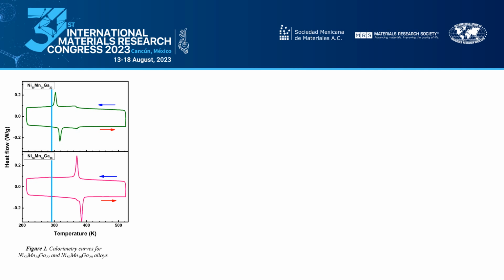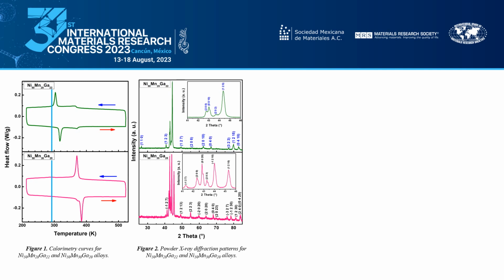In this figure, we can see calorimetric curves for both alloys. It can be seen that the martensitic temperature range is above room temperature. Therefore, in the next figure, the diffraction patterns obtained at room temperature correspond to the martensite phase in both alloys. The first alloy was indexed with the diffraction pattern for a monoclinic crystal structure known as 5M. The second one was indexed with the diffraction pattern for the 7M monoclinic structure.